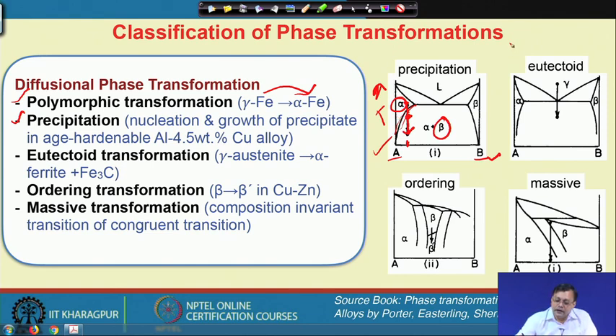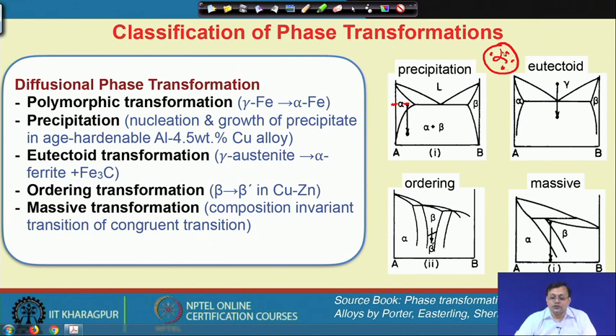What I want to mean is that during cooling, let us assume that this is the microstructure of alpha, which is kept at this temperature, and so beta will nucleate here, nucleation of beta will occur, and then they will grow. So, this is a precipitation phenomenon, because from one solid we are getting another solid which is precipitating from the parent matrix. There are very similar phenomena observed in an age hardenable aluminum copper system.